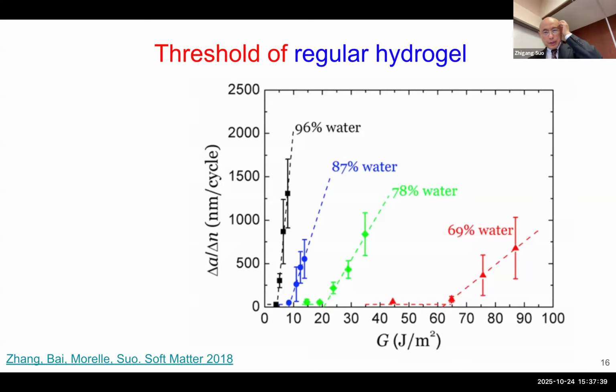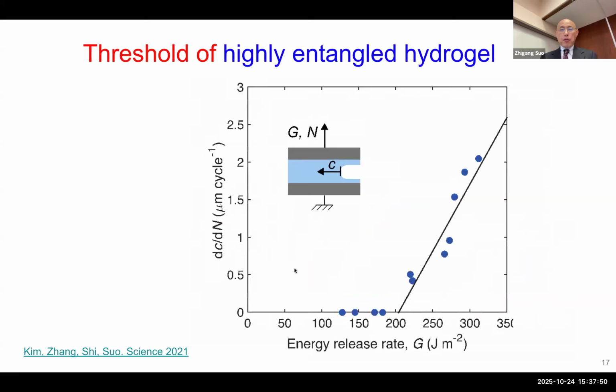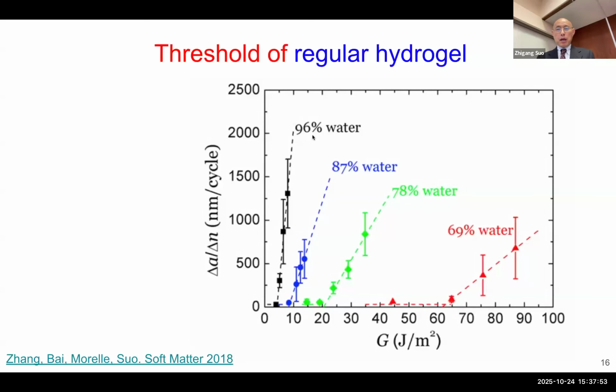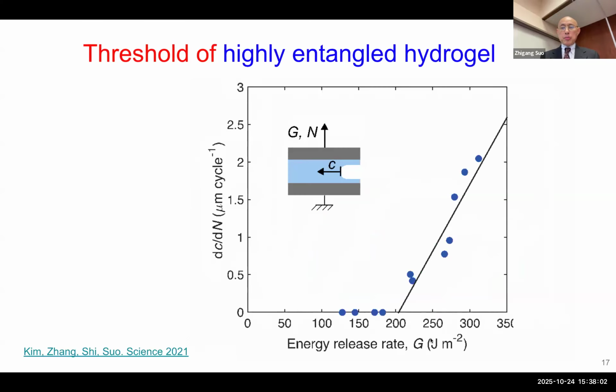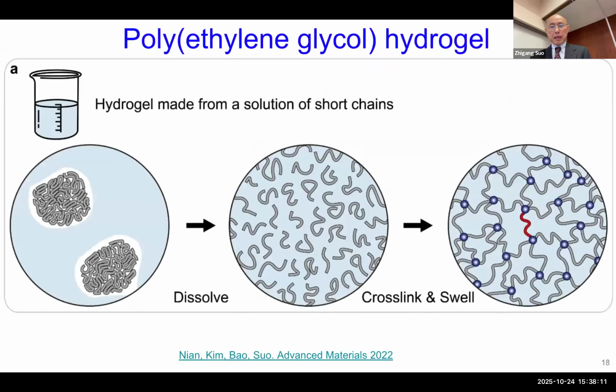Now fatigue threshold. This is a regular hydrogel. This was done by an old student. It depends on the water fraction. We have some range for the ordinary water fraction, 90, 80%. You have a fatigue threshold below 10 joules per meter squared, very low. But for Tanglemer, we reach 200, right? By at least an order of magnitude difference. No problem, easily. So he was very happy about that.